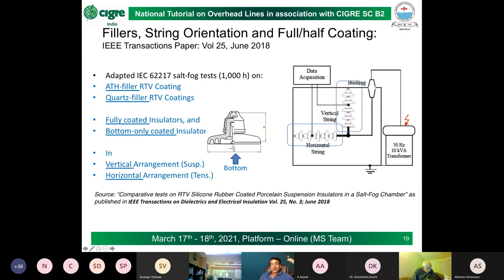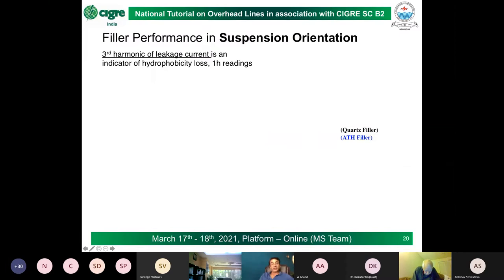I will not go into too much detail here, but this is a paper by Dr. Edward Cherney, who has played a lead role in RTV coating. Terna calls him the father of modern RTV coating. Dr. Cherney assisted me with this work, and he worked also largely with a gentleman from Istanbul University. We looked at the different fillers, the ATH filler, the quartz fillers, fully coated insulators, bottom-only coated insulators, and saw how they perform in the 1,000-hour tests when vertically aligned, like a suspension insulator, and then horizontally aligned. So that's essentially what this test is.